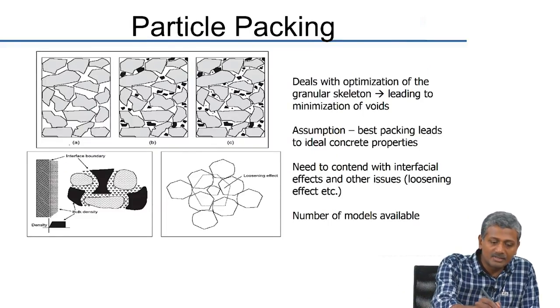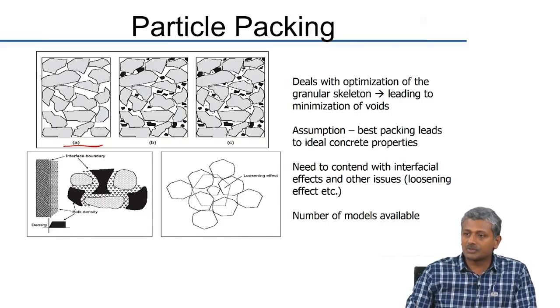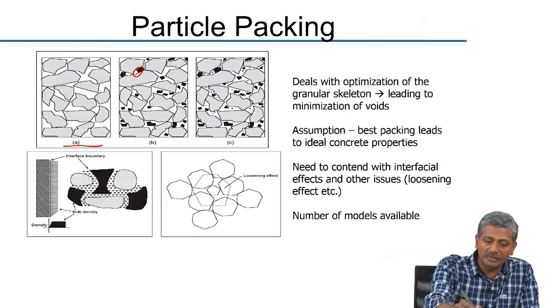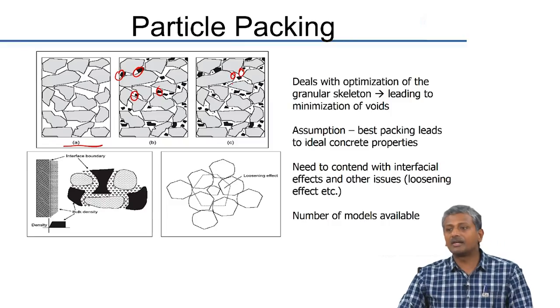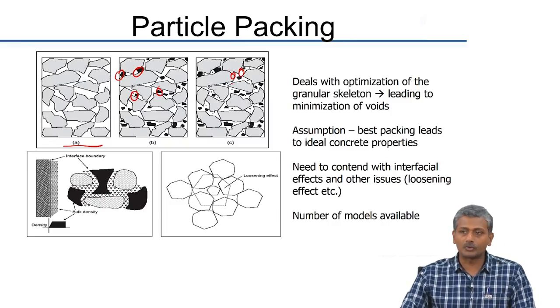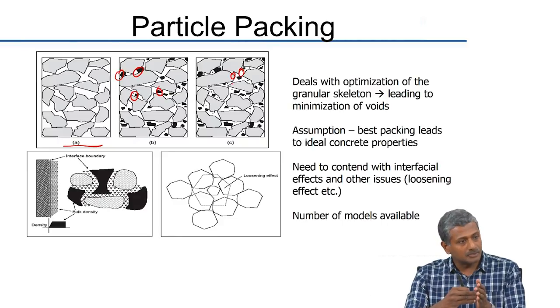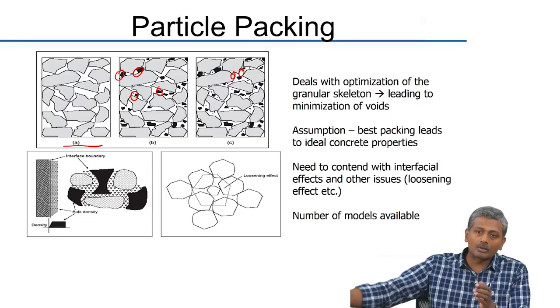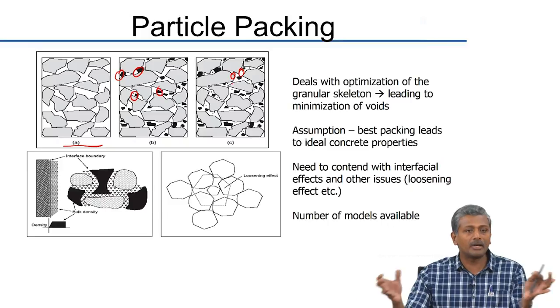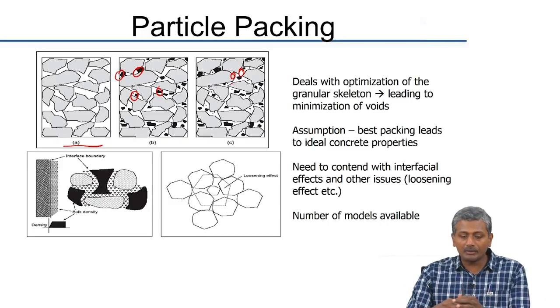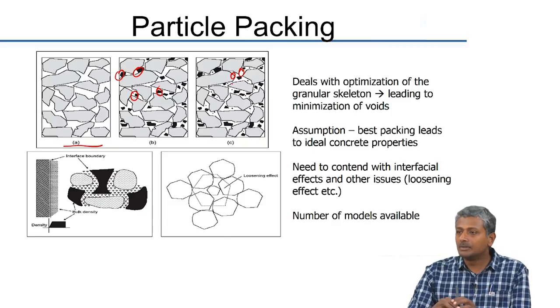If we try to incorporate fillers along with other fillers sometimes used as aggregate replacements, we need to start considering particle size gradations which are more reflective of the actual sizes in the concrete. When Fuller's formula was derived, the maximum size of aggregate was maybe 20 to 40 mm, and the minimum was about 150 microns for sand. But when we start putting fine mineral additives into the mix, we are increasingly getting sizes below 100 microns. So how do we propose a maximum density gradation that accounts for the extra granular constituents?